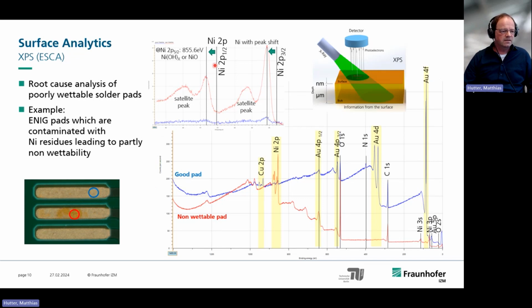And what you can also see is the chemical nature of the nickel. In this case, you see that it's not a pure nickel, but it's a nickel hydroxide or nickel oxide. So this is very unique with this XPS surface analysis tool. And the information depth is only a few nanometers, around 10 nanometers. So you get really information of the surface and not of deeper layers.